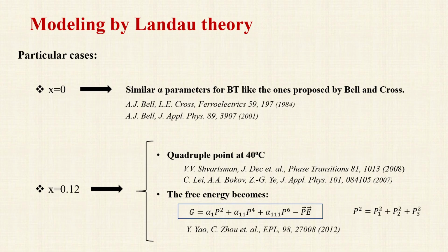In particular, for x equal to 0, the case of pure barium titanate, the parameters are very close to the ones proposed by Bell and Cross for single crystals. For x equals 0.12, we wanted to obtain a quadruple point, as shown in the work of Dec et al. And for this, the free energy should be transformed into a much simpler expression like the highlighted one on the slide, for a temperature of 40 degrees Celsius.